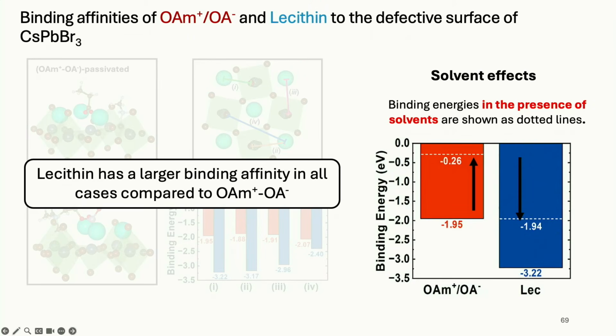And that is when you bind the lecithin to the surface, it binds more strongly than the oleylamine or the oleic acid, that those bind pretty well, but not too bad. But then when you include the effect of solvent, you see the lecithin or these oleylamine and oleic acid, they could just go off and join the solvent. And it turns out solvating the two separate molecules is much more stabilizing than it is stabilizing for the lecithin. So this is the binding of lecithin in the presence of solvent. And this is the binding of these other guys. It's too weak. It's not really fully covering all the sites. It's not passivating all the defects. And that's why we think lecithin offers enhanced resistance to blinking.